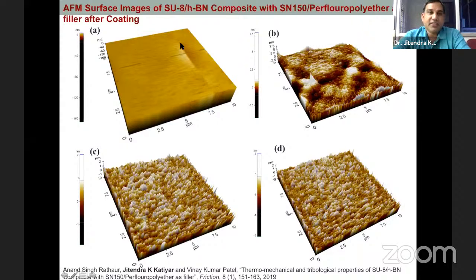So this is the pure SU8, and after adding the hexagonal boron nitride solid filler, the surface looks like this. Then after adding the liquid filler, it can perfectly fill the bigger pores, and it gives a very smooth nanotexture over the surface.